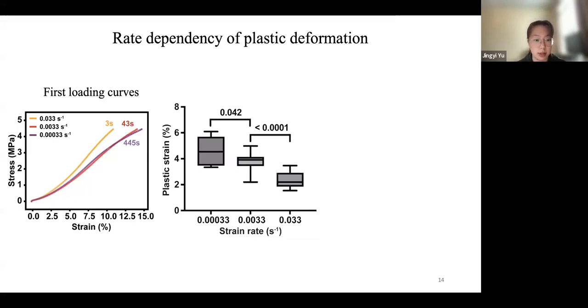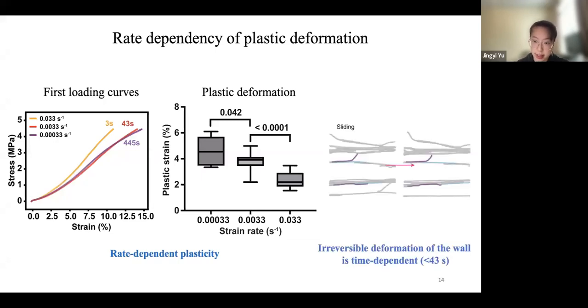And we further examined to test if this is also reflected in the residual plastic strain. We measured the plastic strain after the first loading, and we found that indeed we only see a difference in plastic strain when we stretch the cell wall at very high speed. So overall, this is showing that the plastic deformation does show a certain degree of rate dependency, but only when we stretch it very fast. And by looking at the time scale, it is indicating that it probably requires a relaxation time in the range of about 3 to 43 seconds.